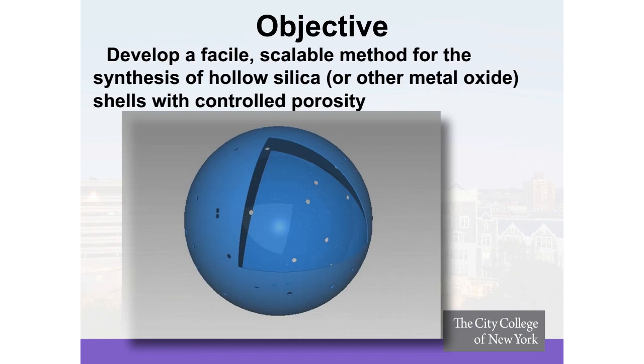By controlling the porosity of the shell, we can now have a scalable way of synthesizing hollow silica particles or other metal oxides, and we can control the exchange rate between the inner and outer domains by controlling the number density of the pores and the size of these pores. These pores again are templated by the presence of polymer chains that are incorporated in the actual vesicle wall.